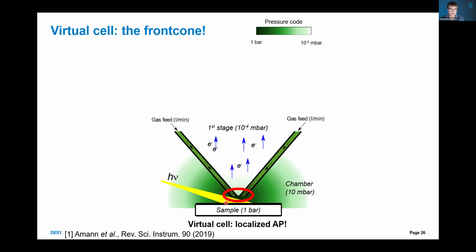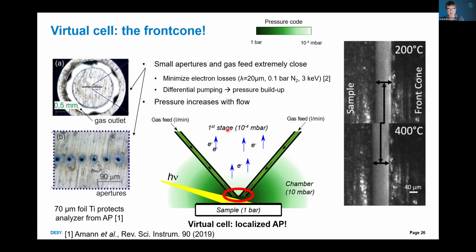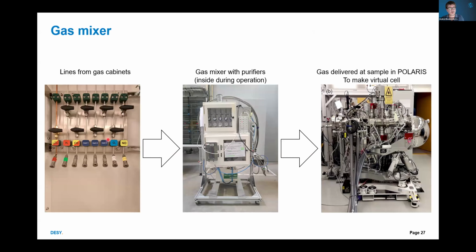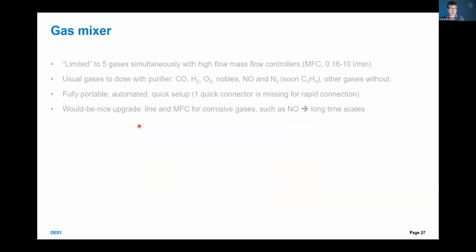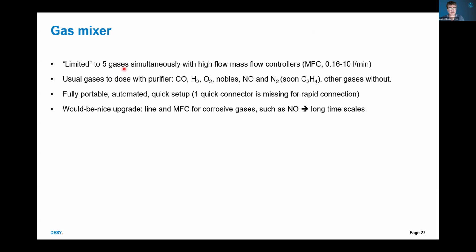So we create the pressure at the sample position, while at the first pumping stage we have already a decent vacuum of 10⁻⁴ millibars. And then the electrons, when they travel towards the detector, arrive at good vacuum. The trick is that the distance from sample to the front cone is very small. It's about 50 microns or even less. And we also offer a gas mixer, which allows us to mix 5 gases simultaneously.